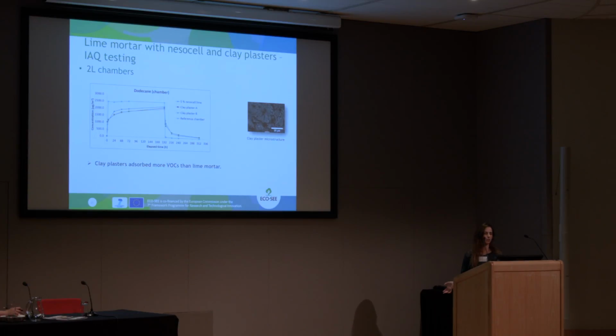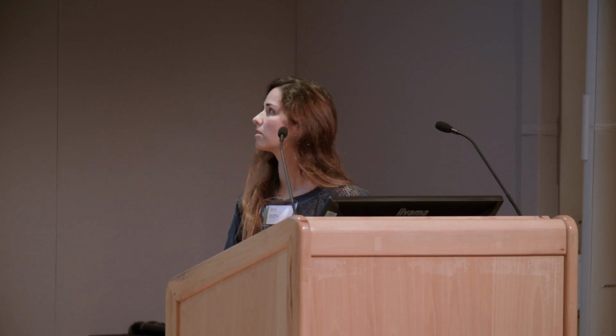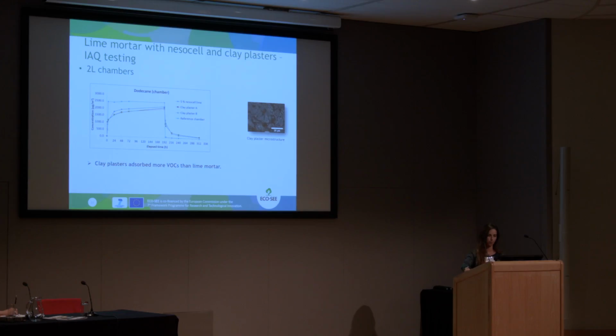This is a comparison between lime mortar and clay plasters, and we observed that the clay plasters absorb more VOCs than the lime mortars. This is because the clay plasters have these irregularly shaped particles from the clay, and thus the surface area is higher.